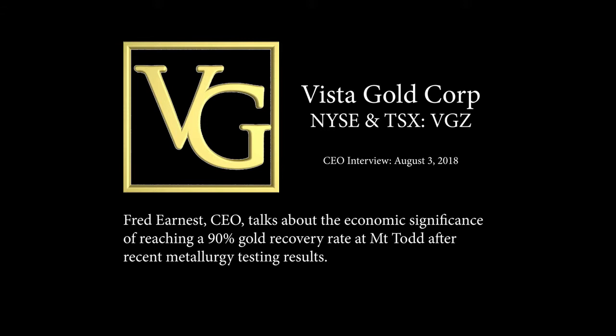But the technology that we selected, the stirred mill grinding technology, is the regrind circuit. The metallurgists that worked for us just said, when you grind this material in an actual mill, you will see another improvement. And we weren't quite expecting the magnitude of the improvement. We were hoping 1% or 2% maybe. But the rock has surprised us, and I guess really not surprised us. What we're seeing is that as we break the particles down finer and finer, they're starting to exhibit more of the characteristics of the fine-grained sediments, the siltstones and shales that are the host for this deposit.